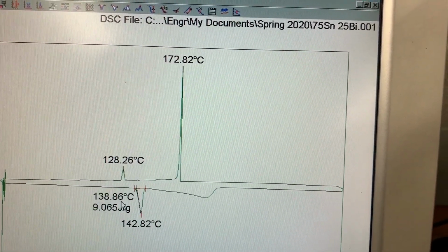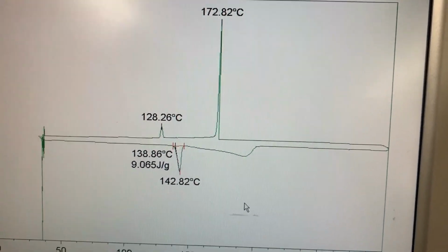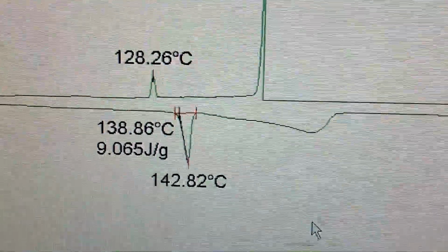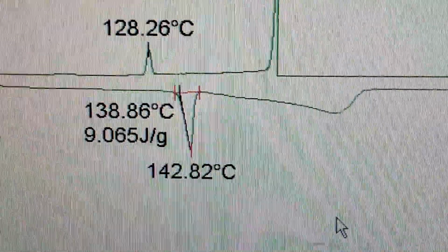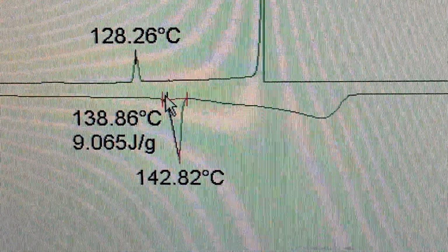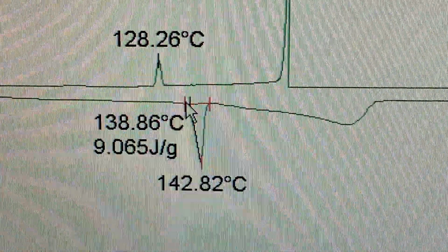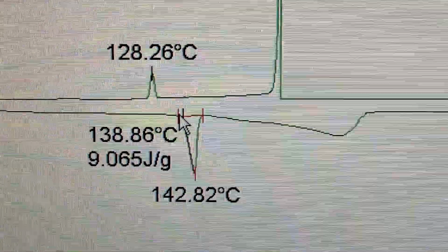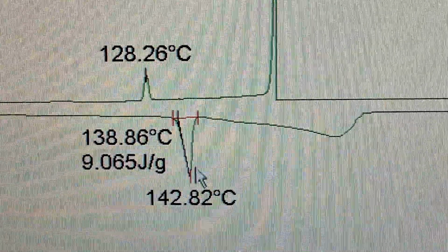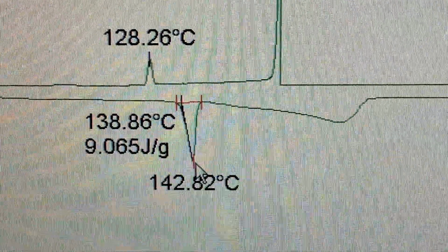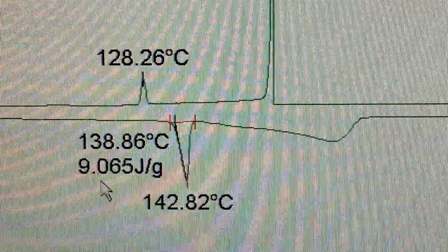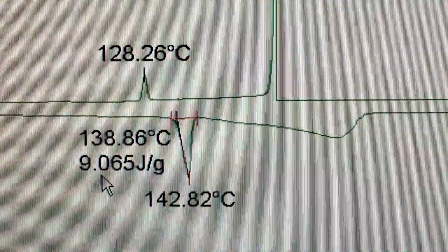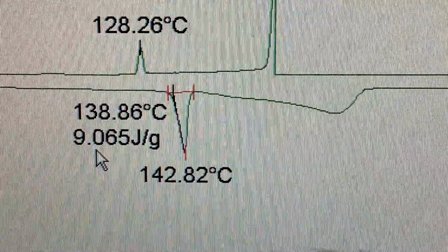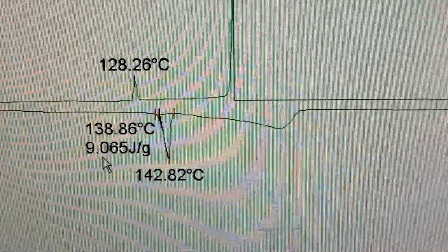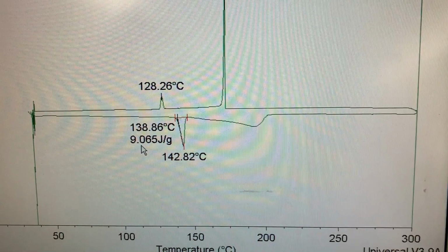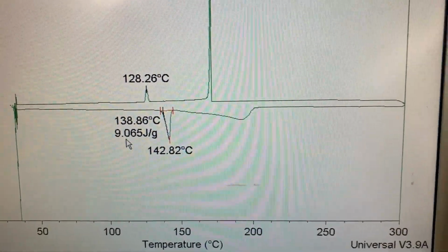You can see here, this one gives us three numbers. So what they mean is that the first number, the 138, is the temperature at which it starts melting. So there's no one specific temperature, it's a range. It starts at 138, and the peak is at 142.82 Celsius. And this number over here, the 9.065 joules per gram, that's just how much energy you require for that specific part to melt, that specific material.